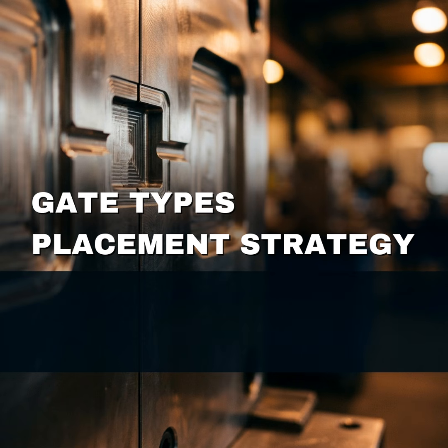Sounds ideal, but I'm guessing there's a catch? There always is, right? The biggest downside is gate removal. It's difficult, and you're almost always left with a visible gate mark, which can really affect the product's aesthetics. You get a lot of heat concentration and internal stress around that gate, which can lead to defects like sink marks. And for thin-walled parts, especially with crystalline plastics, you can see deflection.